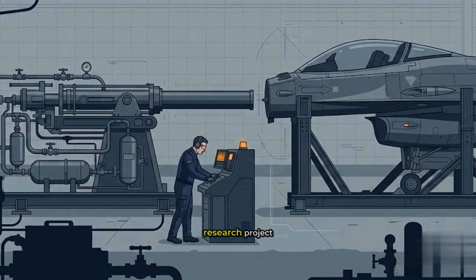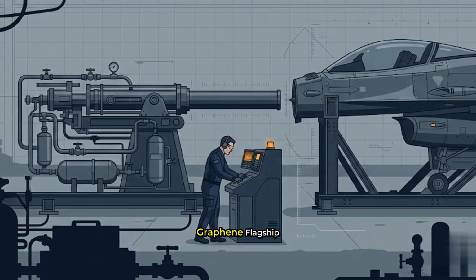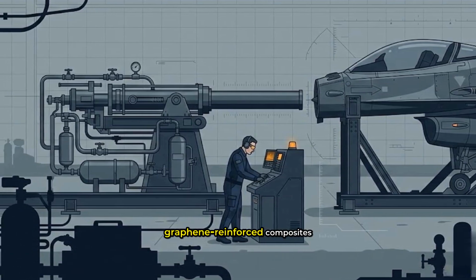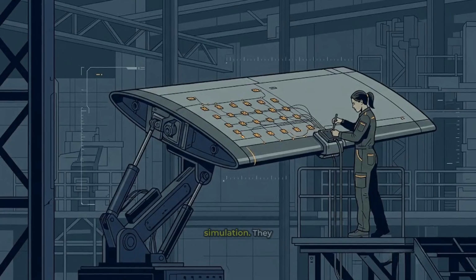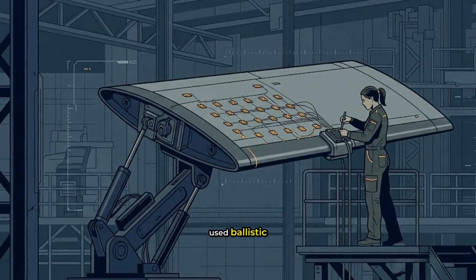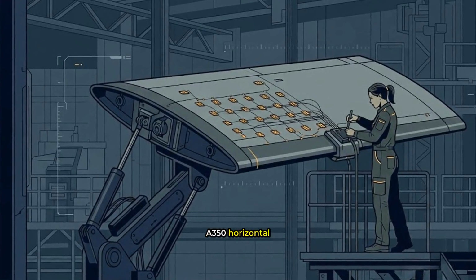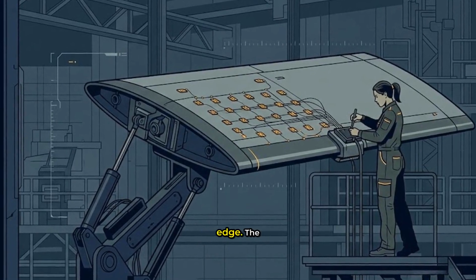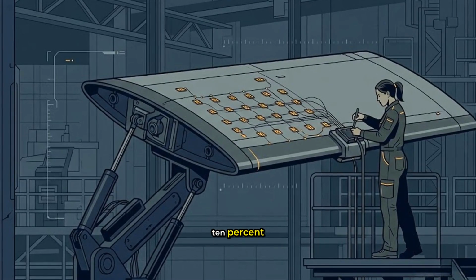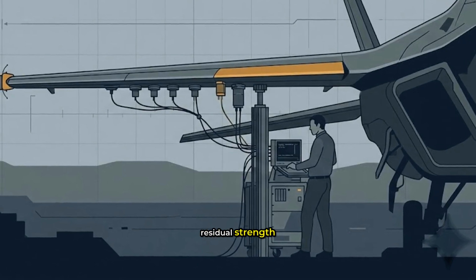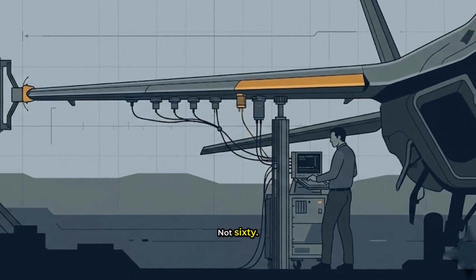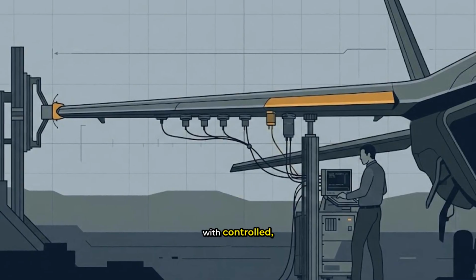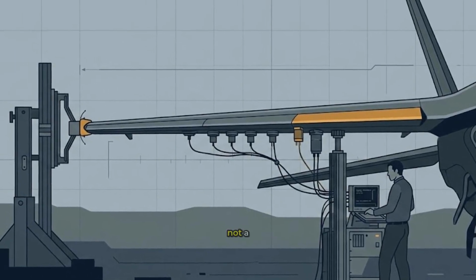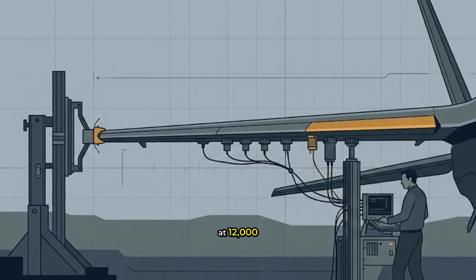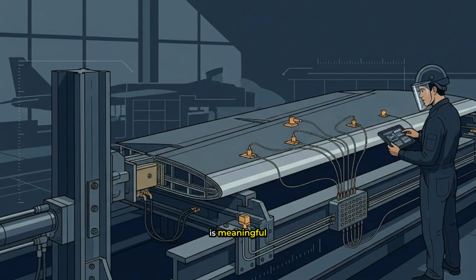One European research project under the Graphene flagship did test graphene-reinforced composites for bird strike simulation. They used ballistic gelatin projectiles on an A350 horizontal stabilizer leading edge. The result? A 10% improvement in residual strength after impact. Not 60, 10. And that is with controlled, low-velocity impacts, not a full-speed encounter at 12,000 feet.